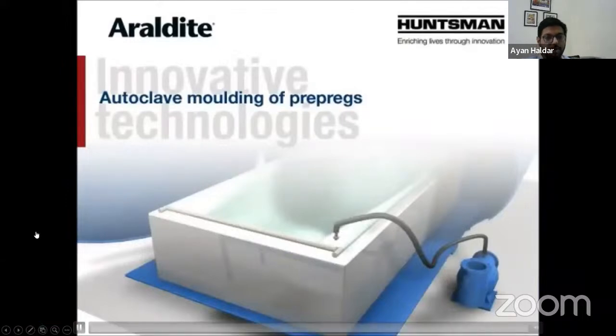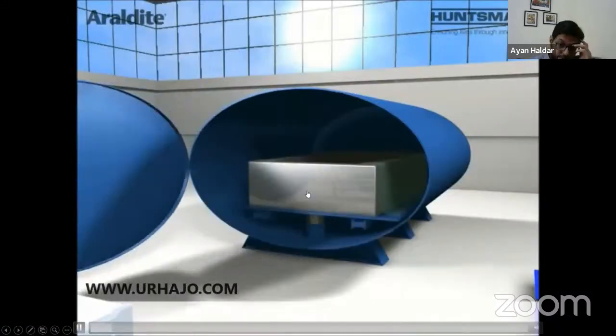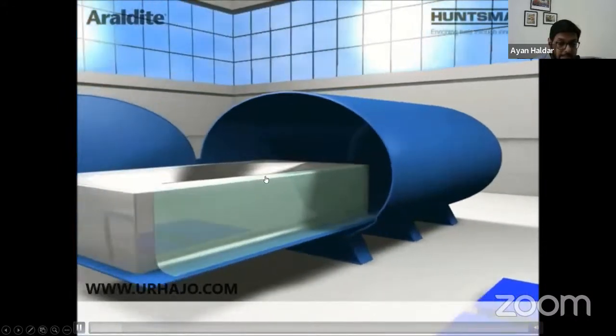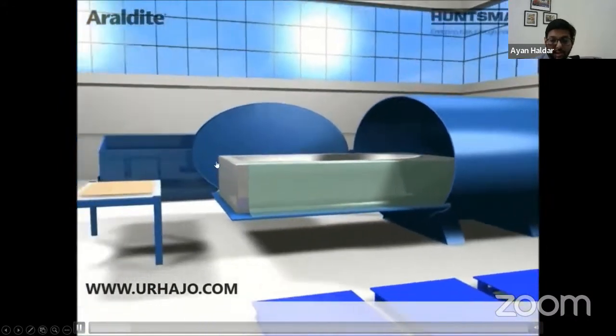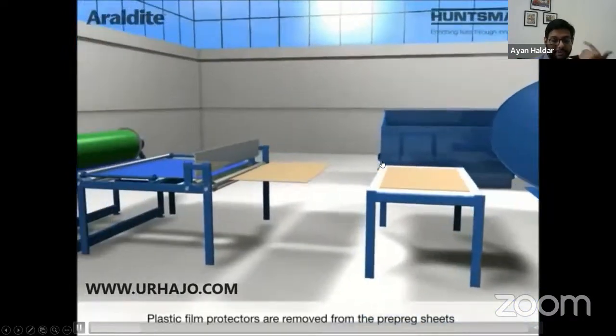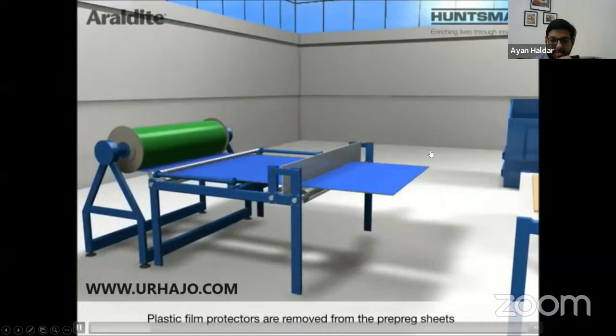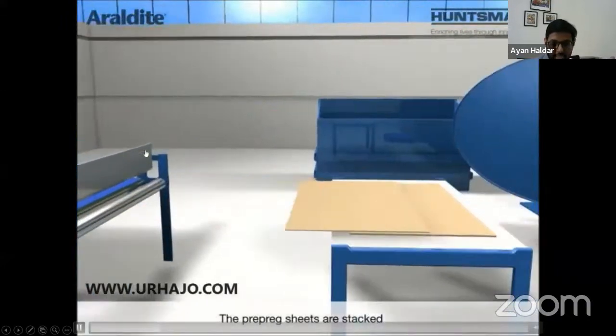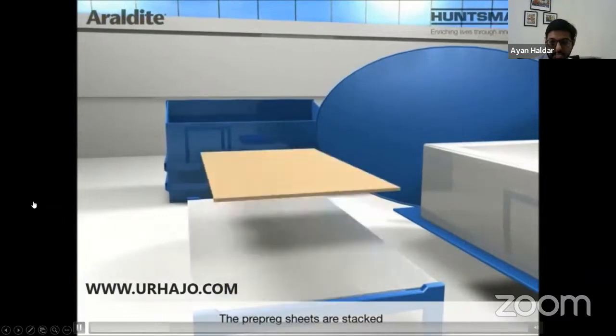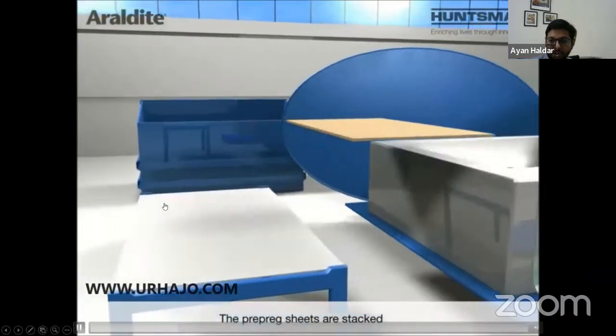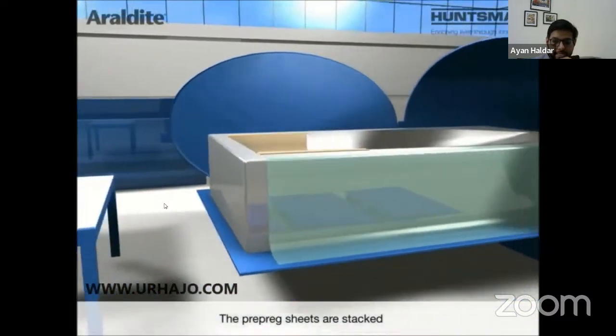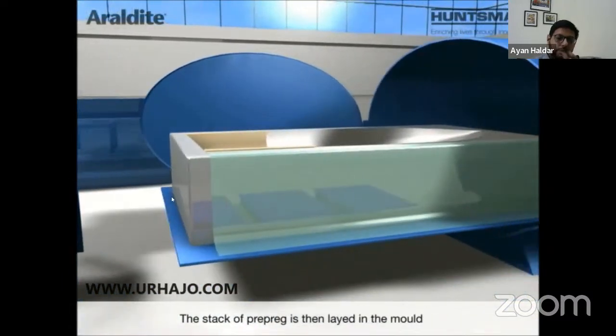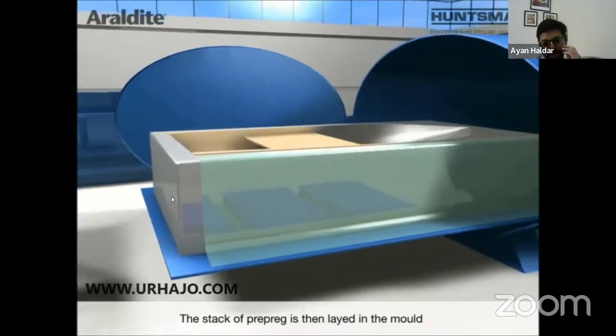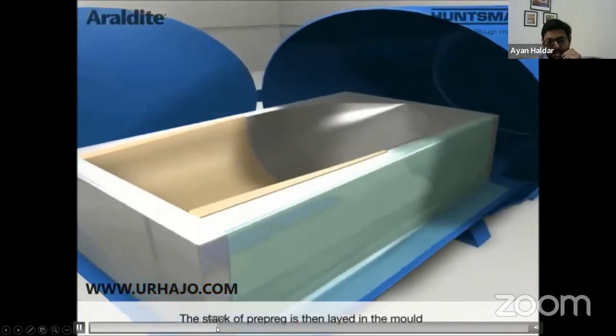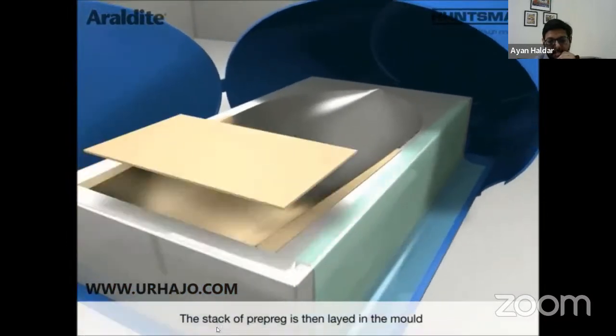This is an autoclave molding of prepreg. So this is how an autoclave looks like. You have a plate that consists of the mold. So you prepare this mold earlier, let's say made of stainless steel, or something which can take this high temperature. And these are the prepregs. You cut it, and this is a cutting table. Using this cutting table, we cut it and then accordingly put it over a particular mold like this. And then you put the stacking sequence, depending upon your application, and then you put it inside the oven.